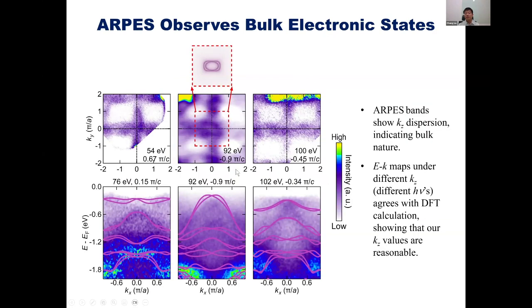First of all, we would like to tell you that our ARPES measurement actually measures the bulk band instead of the surface band, because the spin splitting in the surface band is irrelevant to our discussion. It's not a property of the altermagnet, the spin-split antiferromagnet. We can see from this figure that it has kz dispersion, meaning that the bands we see actually come from the bulk of the crystal.